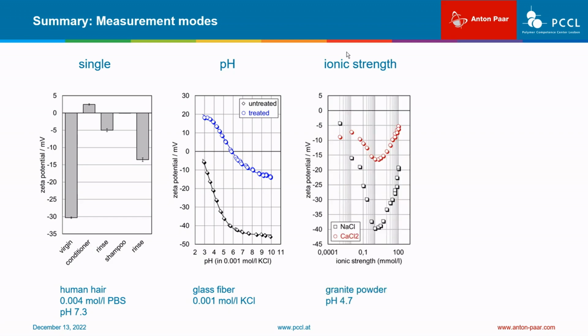The dependence of the Zeta potential on the ionic strength of a complex electrolyte, other than monovalent ions, indicates any specific interaction between these ions and the solid surface, such as adsorption, complexation, or even chemical reactions.